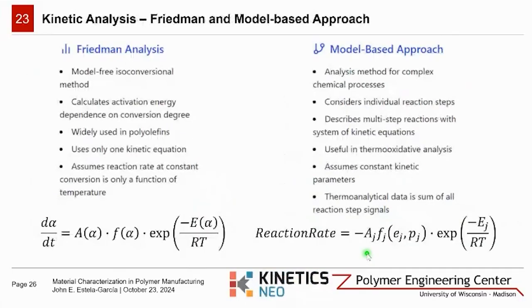So with the data demonstrated before, particularly the virgin one, we're going to employ two distinct approaches to kinetic analysis. We're going to apply the Friedman method, and then we're going to apply a model-based approach. The Friedman method is widely used for polyolefins. It calculates the activation energy of a reaction as a function of conversion degree. And this approach is particularly valuable for simple systems and is very much prevalent in pyrolysis modeling.